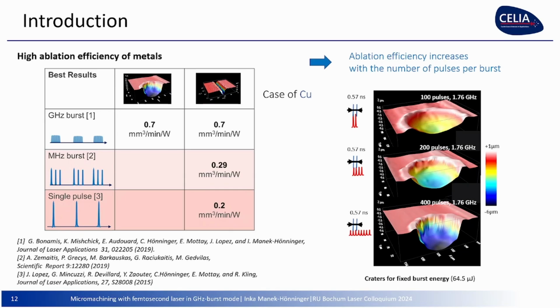These craters are in copper. When you increase the number of pulses, you keep the intra-burst repetition rate within the burst. You just add more and more pulses. What you can see is that you increase the ablation. This is what we saw.